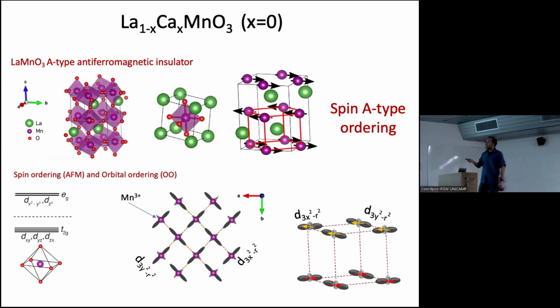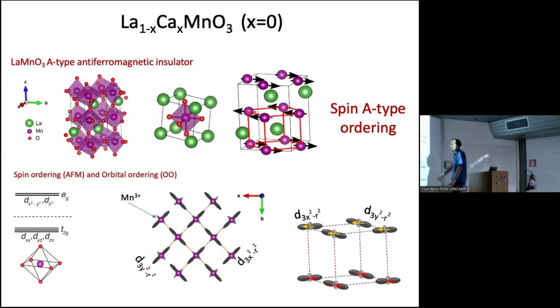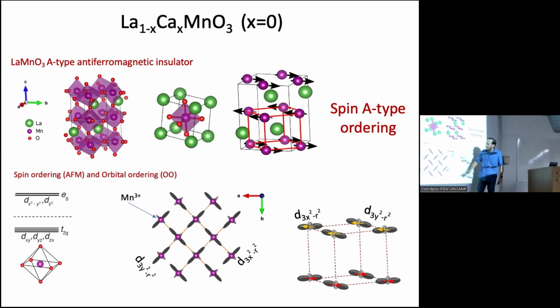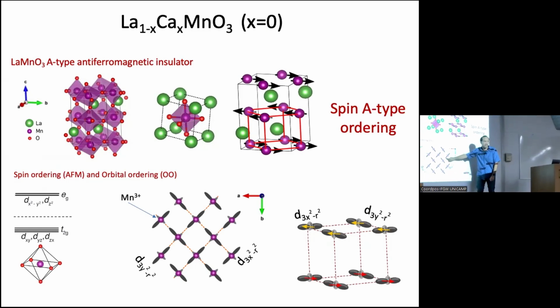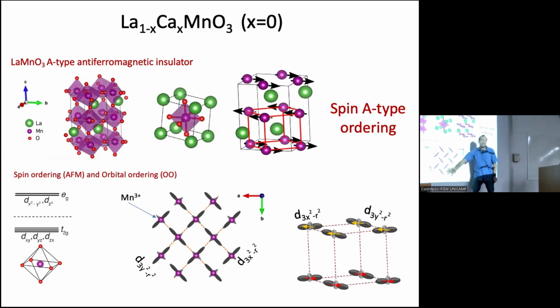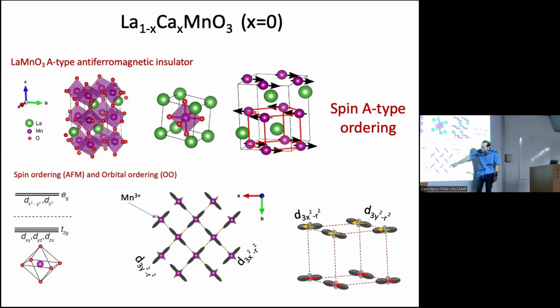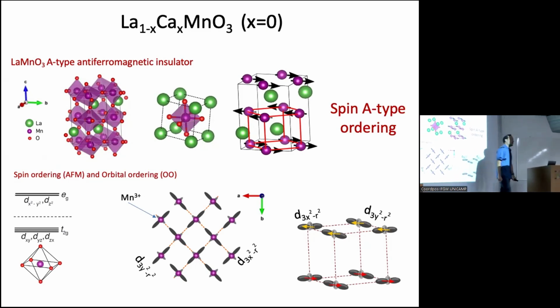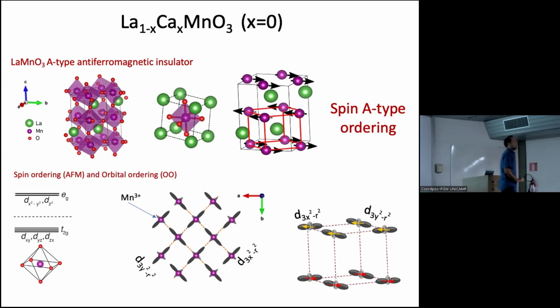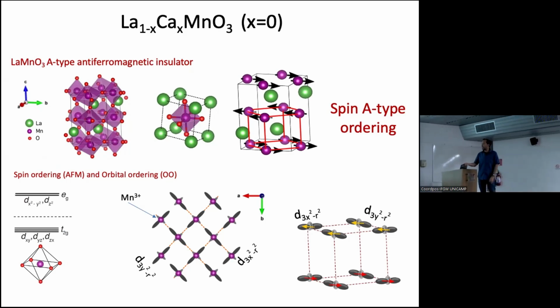So it has this perovskite structure. It has a spin A-type ordering, so the spin has a well-defined spin structure. And then you will see a bunch of these diagrams. I'm trying to put here the manganese ions with the orbitals, and this is the way that they are organized in the lattice. And every time you see these dashed lines, it means that there is an antiferromagnetic coupling. Okay, so here you have everything antiferromagnetic, and it changes depending on how you change the doping, the calcium in this lanthanum in this material.